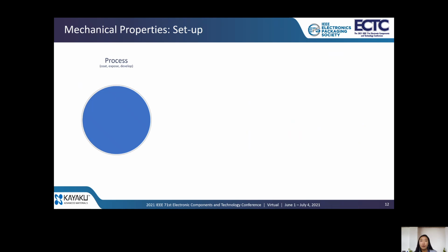Mechanical properties are important to understand the inherent characteristics of materials and the way they should behave in different environments. So for example, elongation is a good indication of passing thermal cycling and drop tests. In last year's presentation, we reviewed the material's modulus at different temperatures to simulate a thermal cycling environment. Additionally, we showed the mechanical properties after a series of high temperature testing. Something we noticed during the development process of this material was that there really is no across-the-board standard for measuring elongation. Therefore, it's kind of difficult to compare different material types' mechanical properties and to be able to benchmark them.